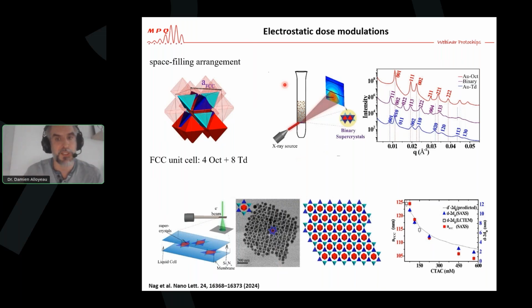And the most interesting result is that we have a way to study the structure of those supercrystals and obtain the same type of structure, and more importantly, a tunable and controlled lattice distance, both in agreement with SAXS experiments and liquid cell TEM experiments. So really, these types of tools are extremely important to make experiments possible and much easier to run. So that's really a great improvement for in-situ TEM experiments.